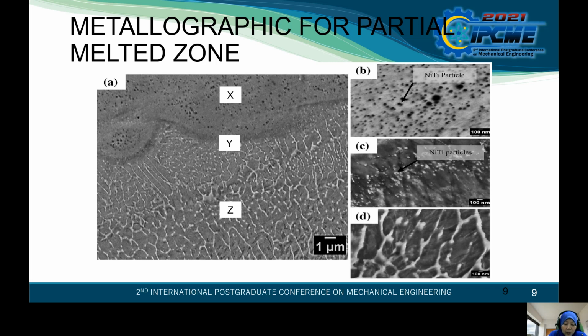Grain structure observed in region Z were formed as a result of lower solidification rate relative to region X and Y. When the heating hit, a small percentage of nickel titanium particle melt in the substrate and was pushed to region Z by high irradiance laser beam. As the laser energy penetrates deeper into the sample depth, the cladding surface solidifies at lower cooling rate. Thus, grain refinement appears in region Z and varies as a result of the heating and cooling rate at different laser parameter settings. Overlap laser spot in the sample cause additional heating of the clad layer which delayed the solidification. In laser surface modification, rapid localized heating and cooling produce smaller grain size and initiate phase transformation. Laser power affected the clad layer width and depth formation on the substrate.